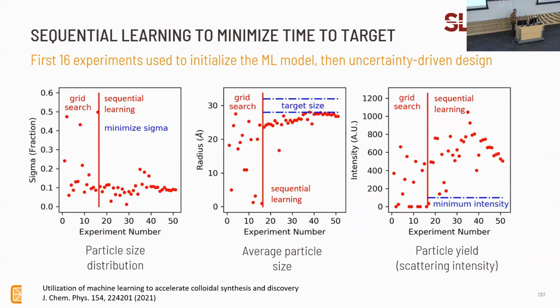Again, this is all published, but these are the figures that show, as a function of the experiment number, how the sequential learning did in terms of finding this optimum. These are 3 different metrics that they were trying to optimize simultaneously. With our software and with most of these methods, you can do multi-parameter optimization. They were looking at the sigma, which was the particle size distribution. The smaller that is, the narrower the distribution is, the closer it is to a delta function. The particle radius, you're trying to hit some particular target size. And then the intensity, which is equivalent to the particle yield, and you want to minimize that.